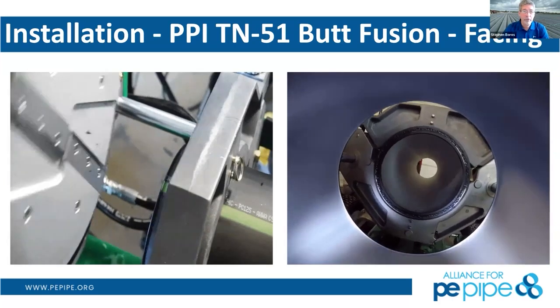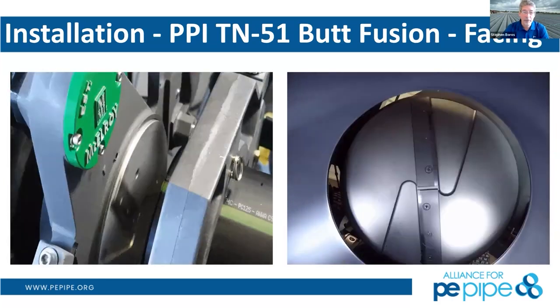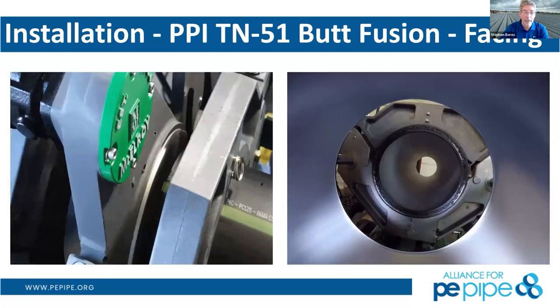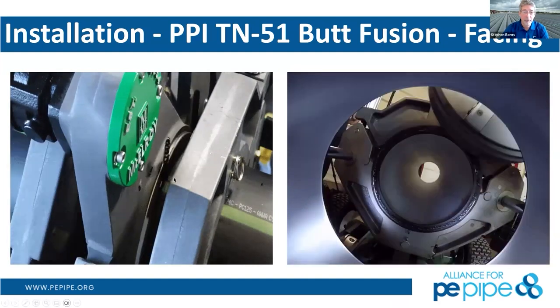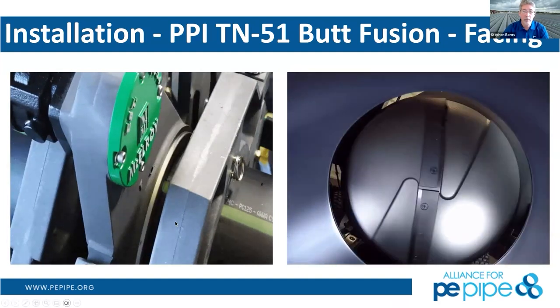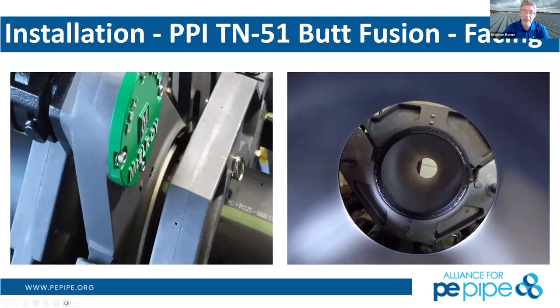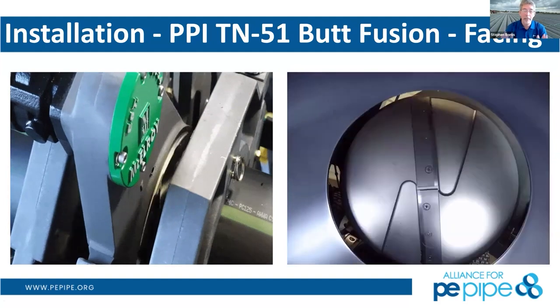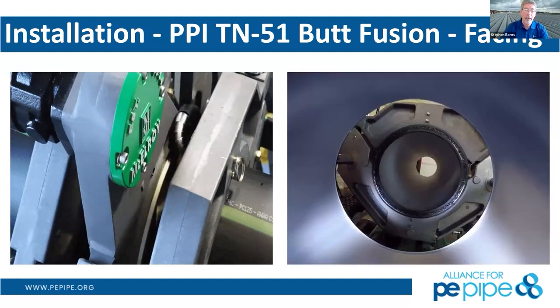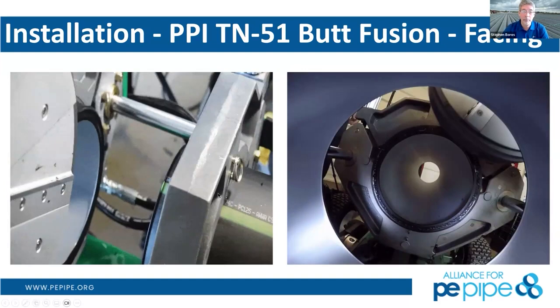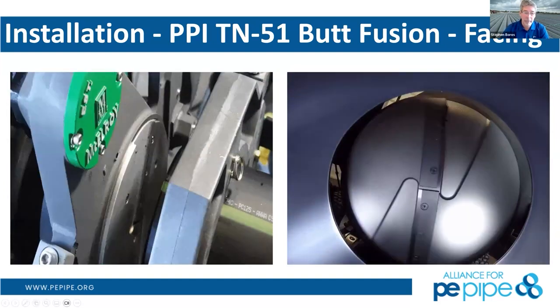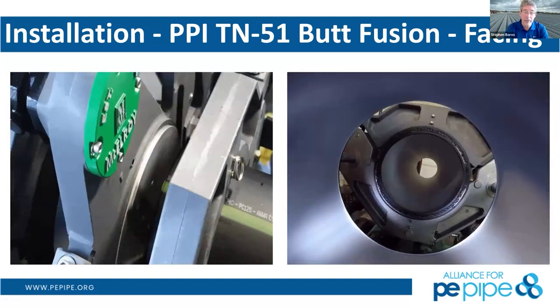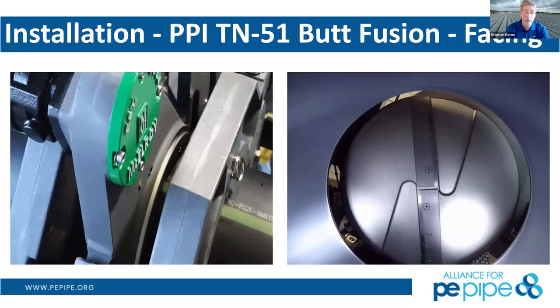So you can see here, the first step of that is to face the ends. You put the pipe into the fusion collets and you bring both ends together, and these blades spin slowly around it. And that gives you nice, clean, uniform, parallel surfaces. So the pipe comes together in a nice, uniform manner. So this is the first step in the fusion process, and one of the probably most key parts of it as well.